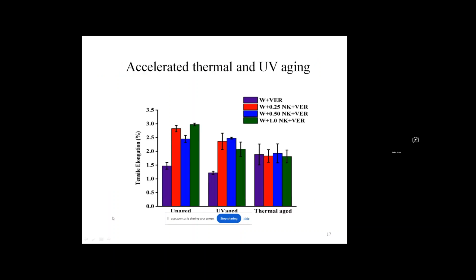So coming to the accelerated thermal and UV aging, we have checked the strength of the composite after aging. So we have performed thermal aging and UV aging. So we found that after thermal and UV aging, the strength of the composite was found to be reduced. And this is one of the products we made using this. This is a tea coaster made from wool vinyl ester composites. Here the wool resin ratio is around 40 to 60.